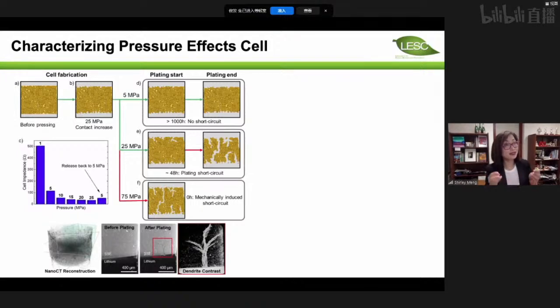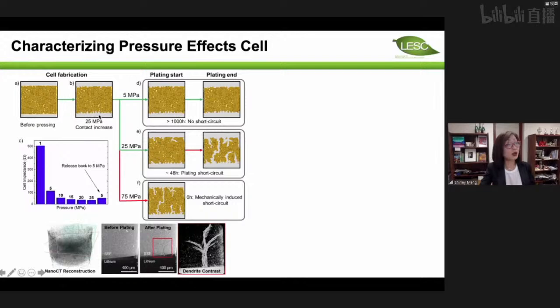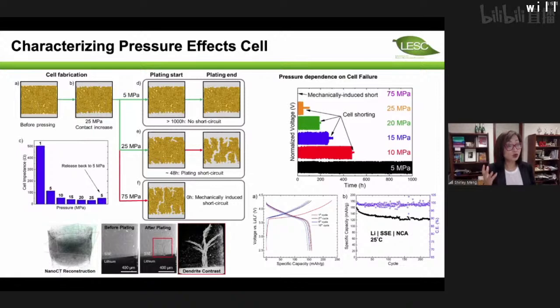Lithium is soft, sulfide is not so soft but still a little bit malleable, and oxide is very hard. So during the synthesis, you need to improve contact by increasing the pressure to 25 megapascal. That reduces the contact resistance dramatically. But during the cycling, if you don't release the stack pressure, you run into a problem called mechanically induced shorting of the lithium, because the lithium will creep into the cracks in the solid-state electrolyte. So to our surprise, the lithium metal anode only cycles when you release the pressure to 5 megapascal. But if you have completely pressure free, if you don't add any pressure, you also cannot cycle the cell. So we are only at the very beginning of lithium metal based solid-state batteries.